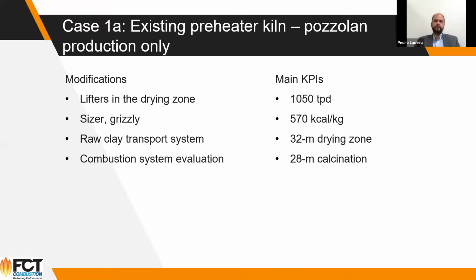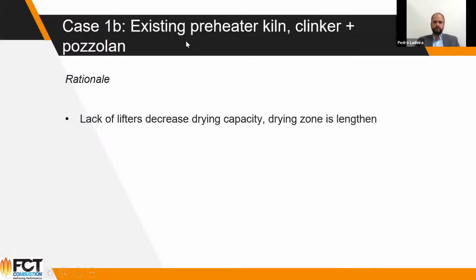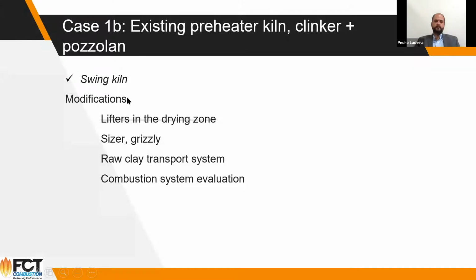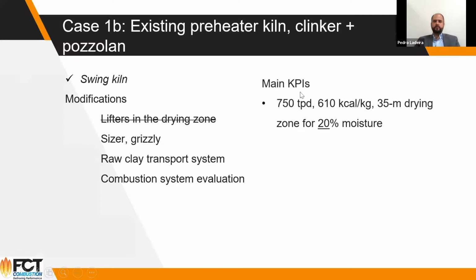But then we go to the other scenario where we want to swing the kiln between clinker and pozzolan. So the rationale, we cannot touch and change, put lifters on that. So we're going to have a lower drying capacity. In this case, we do probably almost everything but the lifters for keeping it as a swing kiln. And this will lead to a 750 tons a day, 610 kilocal per kilo heat consumption. We're going to have a longer drying zone, and we have a 20% moisture removal capacity.